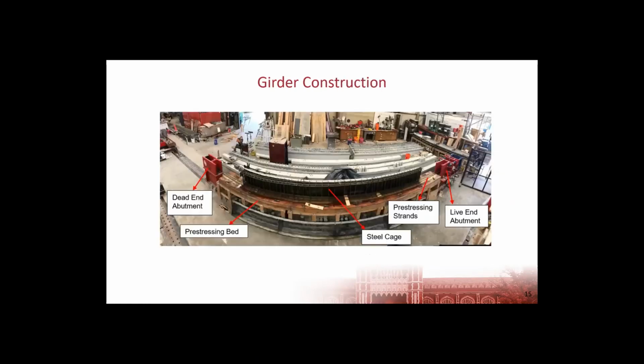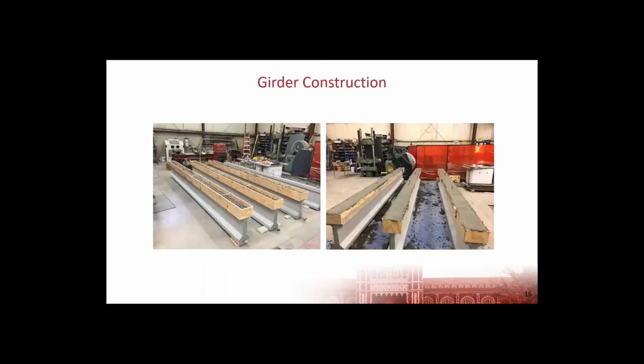We cast these specimens at Fears Lab on the OU campus. We ended up casting them one at a time because of the pandemic restrictions and other projects getting behind. We didn't have as much space as we would normally have to pre-stress two or three of these at a time. But either way, we would put together the reinforcement cage and the formwork, run the strands through, pre-tension the strands with our pre-stressing abutments that are shown here, cast the specimens using a self-consolidating concrete mixture that would gain a strength of about 4,000 PSI in one day, release the pre-stress, and then 28 days later, cast the decks on top of the beams.